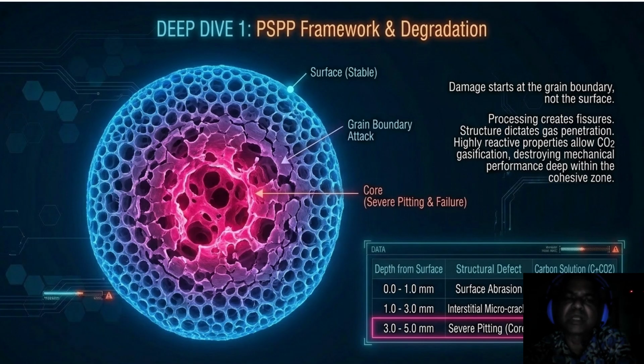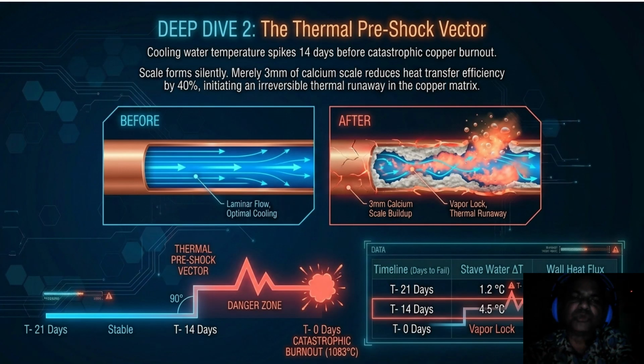While coke failure happens in the furnace, our cooling equipment faces its own silent, irreversible thermal path to destruction. So now in the next slide, we are coming to a deep dive into the thermal pre-shock vector. So let's move to the cooling system and the thermal pre-shock vector. On the left you see the before: laminar flow and optimal cooling in the copper stave. On the right, the after shows 3 millimeters of calcium scale buildup. That scale acts as an insulator, creating a vapor lock.